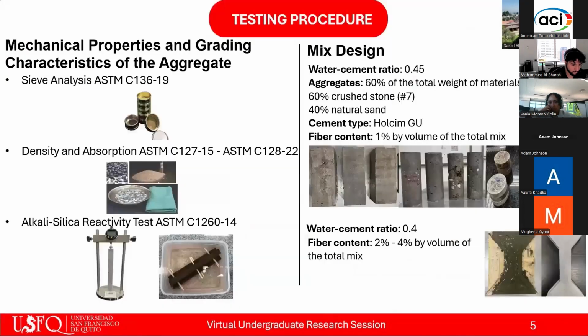The aggregates were first tested for gradation, density and absorption, abrasion, uniformity, and alkali-silica reactivity, following ASTM standards. Two concrete formulations were designed. The first used number 7 stone and sand due to formwork geometry, with a water cement ratio of 0.45 and 60% aggregate by weight, 60% coarse number 7 stone and 40% sand. The cement was type GU, a general use pozzolanic cement in Ecuador.